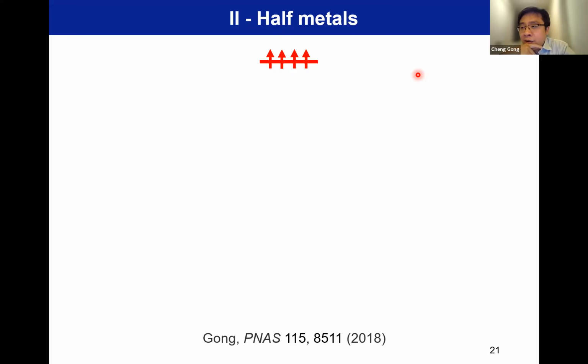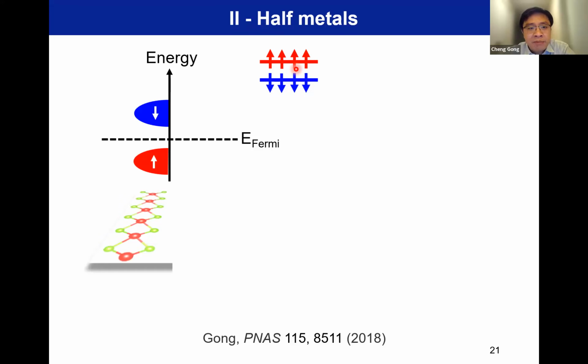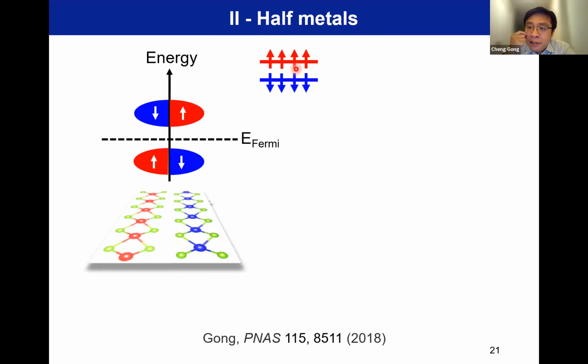You have many ways to define the controlling effect, but one very popular way is, how can we control the spin polarization between 0% to 100% spin polarization. So this part of work is focused on that goal. Now you have a 2D ferromagnet, you have another 2D ferromagnet, but they are coupled in interlayer antiferromagnetic coupling. So this is called A-type antiferromagnet. If you look at one layer alone, that's a ferromagnet, so spin up and spin down bands are split. If you look at the other layer alone, it is also a ferromagnet. But if you put them together, they have an interlayer antiferromagnetic coupling. So as a whole, it does not give net magnetization.